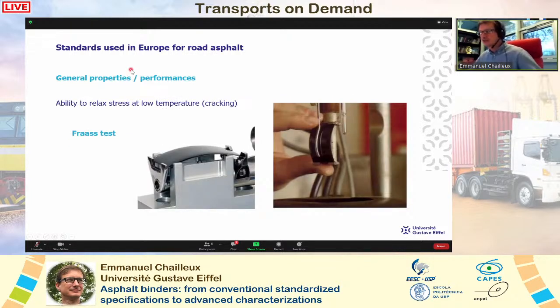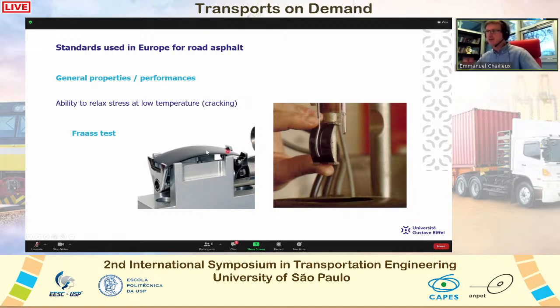At low temperature, in Europe, we still use the Fraass test. The Fraass test consists of a film of bitumen placed on a steel plate, and we deform this system at different temperatures, and we take the temperature at which this film of bitumen breaks.